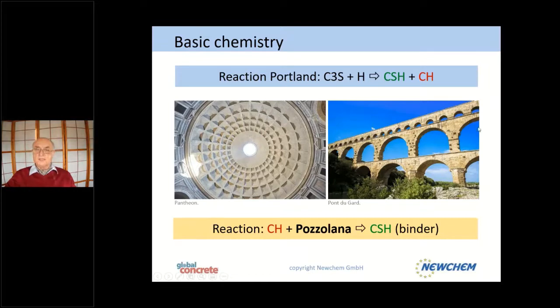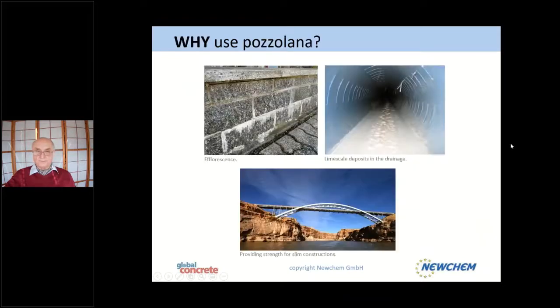And here is the aqueduct from Pont du Gard, which stands almost as long, and it carries water, and it still carries water. Taking into account this reaction, we tried different pozzolanas, and fly ash is naturally one of them, and metakaolin is another one. By this, we produce more binder. You have the same binder you would produce with your Portland cement, and you add new binder by using the reaction of your Portlandite.